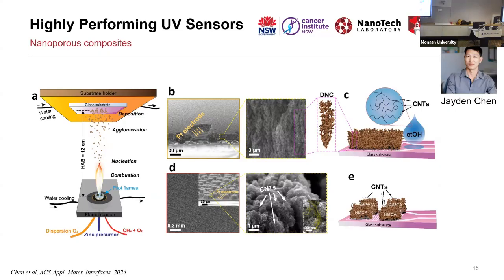Flame spray pyrolysis is great for metal oxide. But if I want to make a composite, for example by adding carbon nanotube, there was no way for me to do that, because it would collapse the system. But now the first droplet changes the structure into this structure, and then in the second droplet, which is not going to change the structure anymore, we add carbon nanotube, and the carbon nanotube goes there. And now we have a composite. You can think of any other materials that you cannot fabricate by flame spray pyrolysis being added into that ethanol droplet, and then into the film.